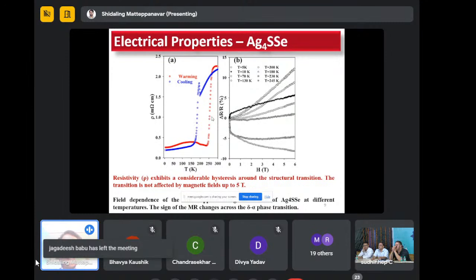And we have also studied the right side part of the diagram that I am showing, that is the magnetoresistance behavior, taken at a few temperatures above and below the transition temperature. The magnetoresistance also shows some kind of opposite or negative behavior when we are measuring the orthorhombic structure, meaning around the structural transition it is showing the negative part.